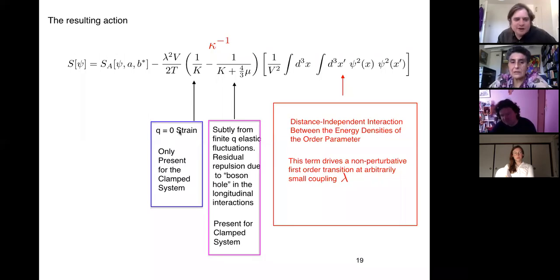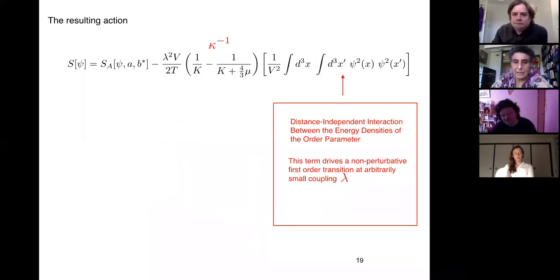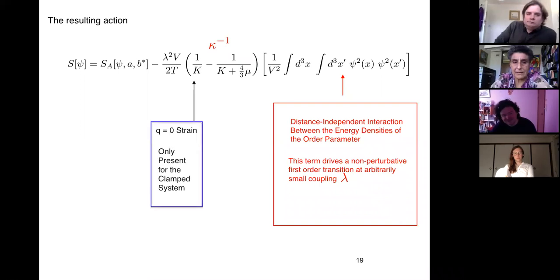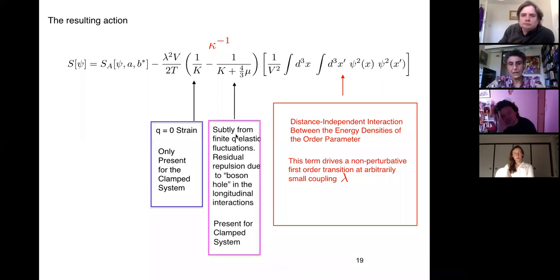Okay, so thanks. Let me go through this again because I made a mistake on the slide. Sorry about this. The Q equals 0 strain is only present for the unclamped system. This has to be changed. This is only present for the unclamped system, and this is an attractive interaction. What's more subtle is this term. This is a repulsive term, and it's subtly from integrating over the finite Q elastic fluctuations.